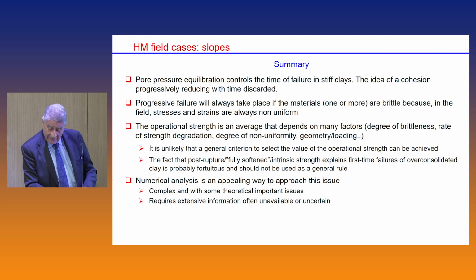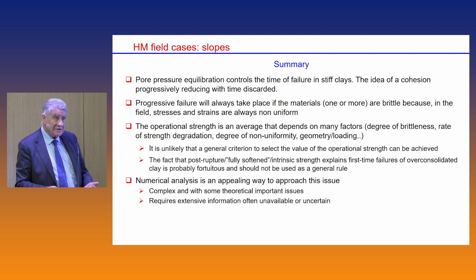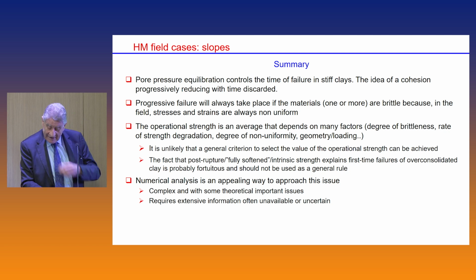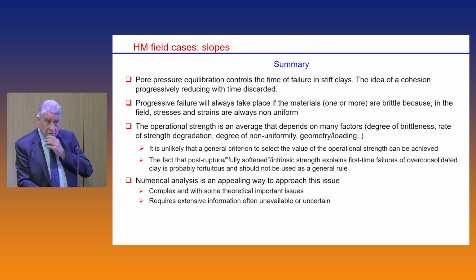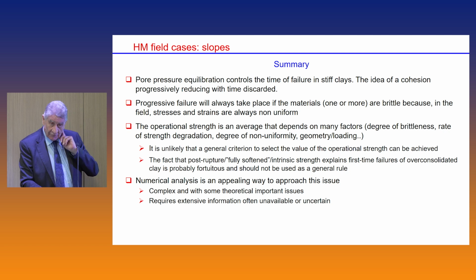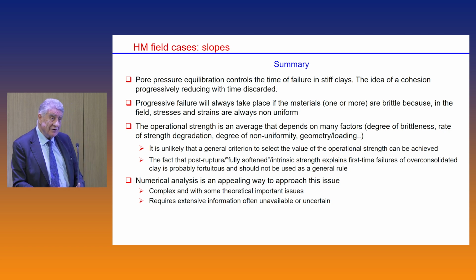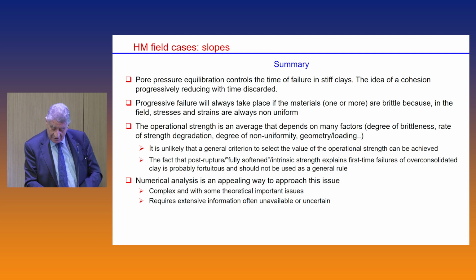So if I summarize this part, it has been demonstrated that pore pressure equilibration controls the time of failure in this type of problem. And if we have brittle behavior, progressive failure will occur because we are always in situations of non-uniform stresses and strains in the field. Because the operational strength, the back calculated strength, the design strength if you like, depends on so many factors, it's unlikely that a general criterion to select the value for design will be found. What has really been abandoned is the concept of fully softened. There is no such thing. The fact that the post-rupture strength seems to explain many of these failures may be a bit fortuitous. Of course, numerical analysis provides an attractive way to tackle this problem, but it is complex and not as straightforward, so I think we are still a long way from this being a routine design tool.